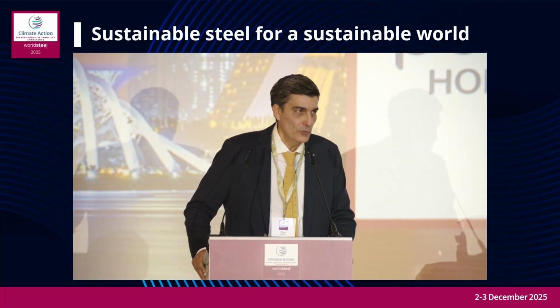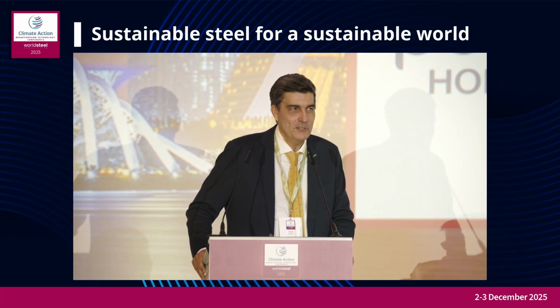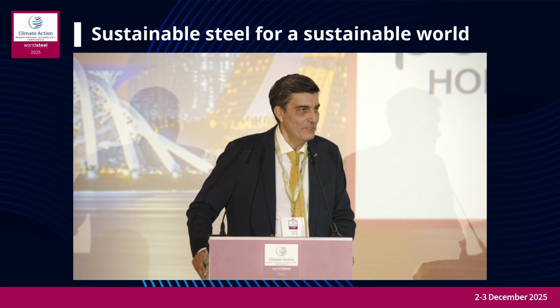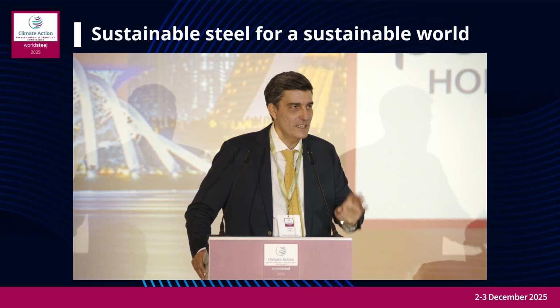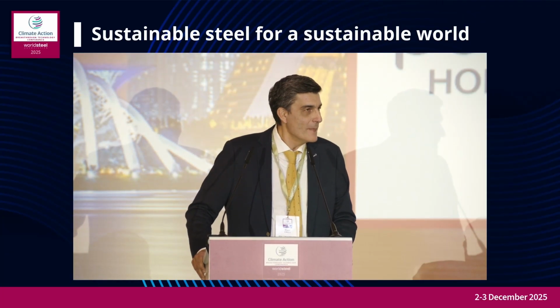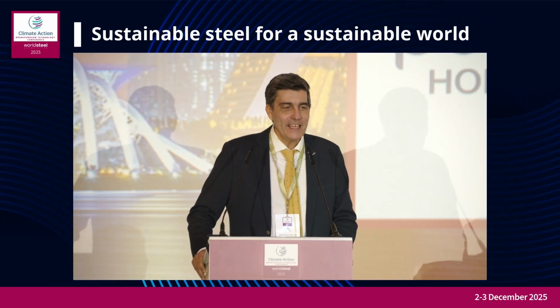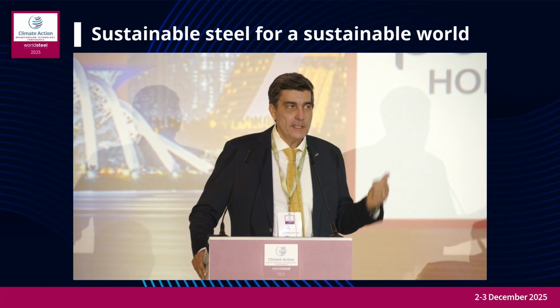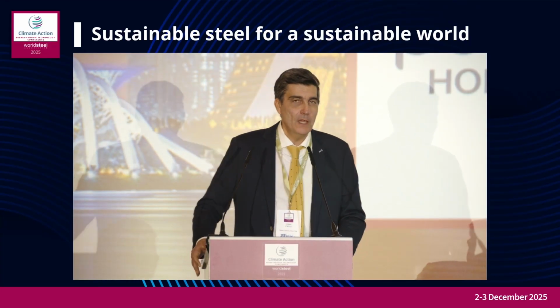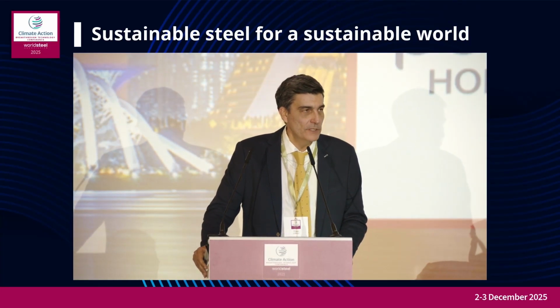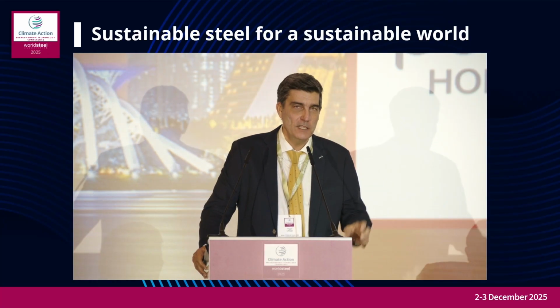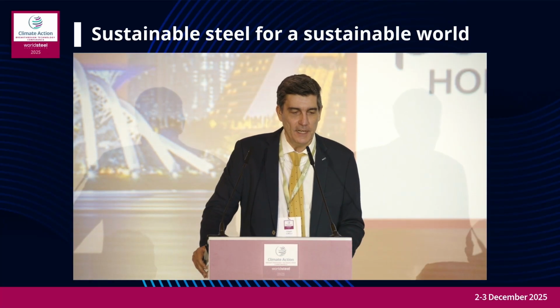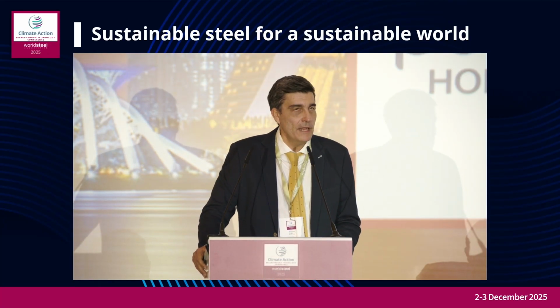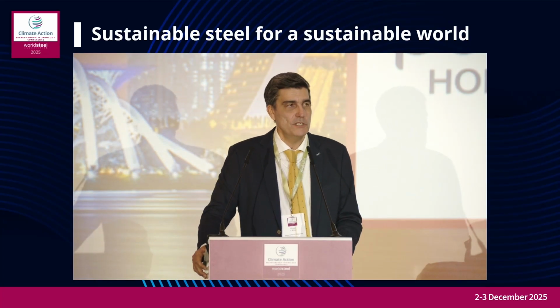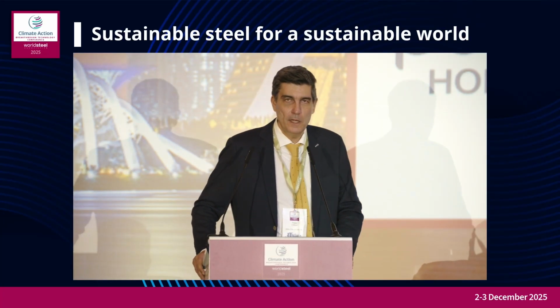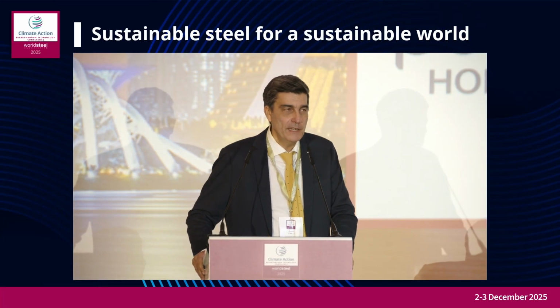This is good to know. When we perform an experimental activity, it's not necessary we are expecting negative results. So when we have positive results, it's the best. Exactly. In this case, the test was performed on MgO carbon refractories and we tested both the slag lining and the steel lining. Maybe you are, and we do not observe significant impact at 900 degrees.